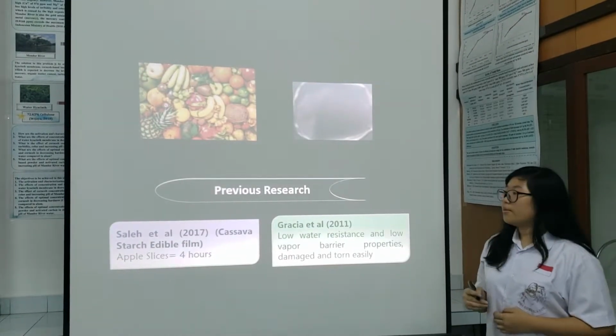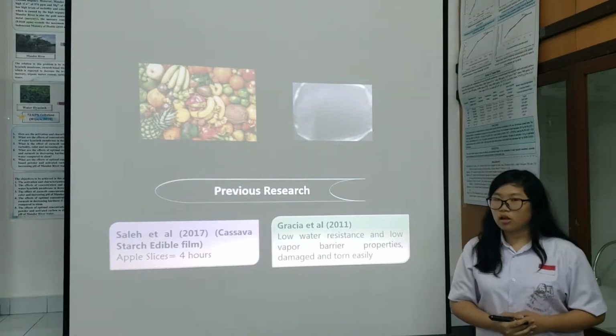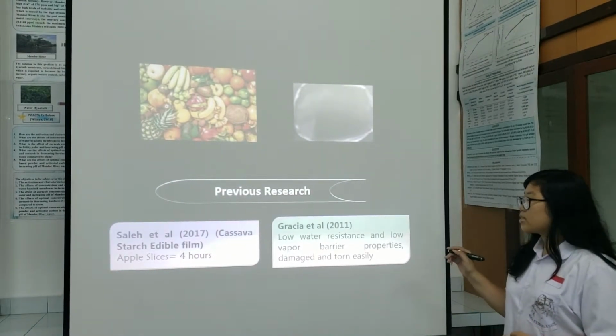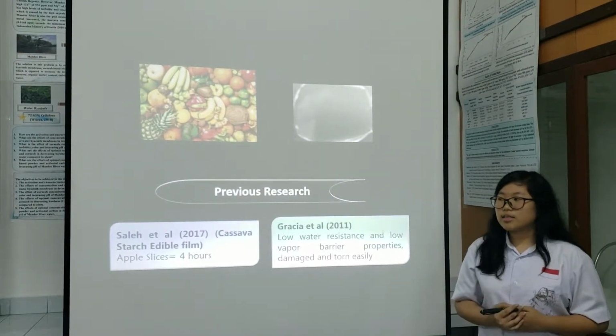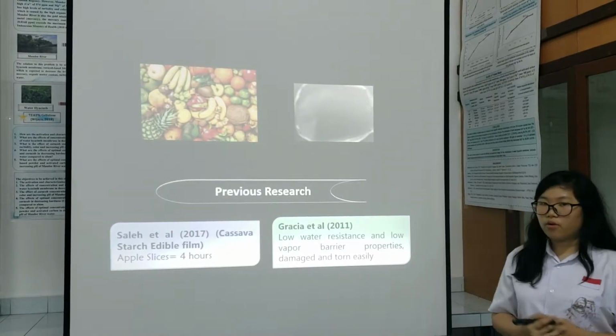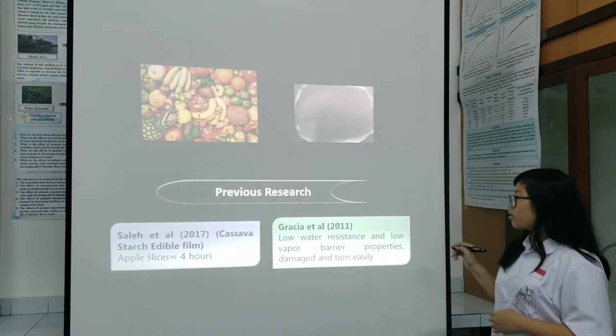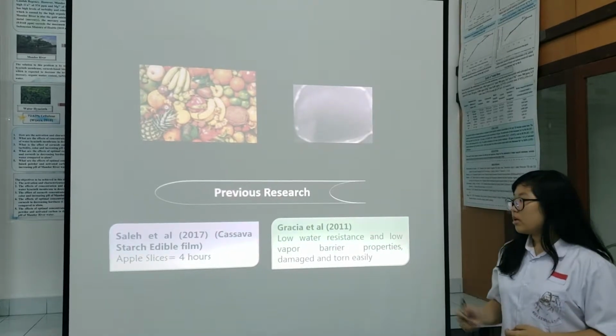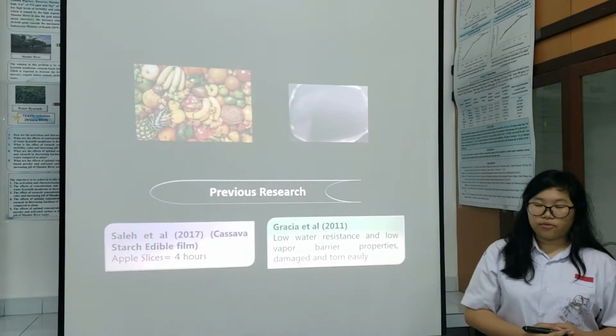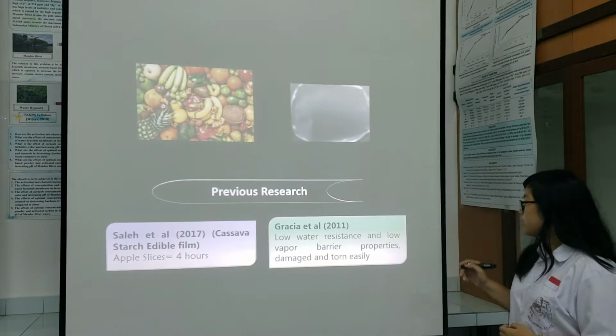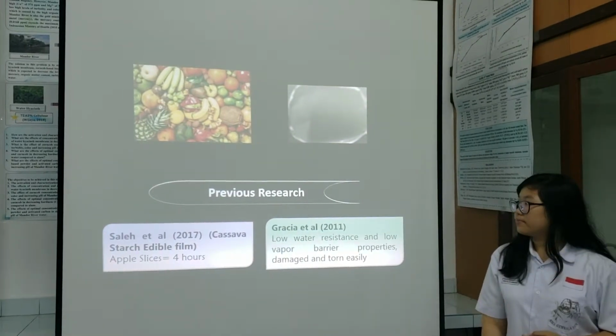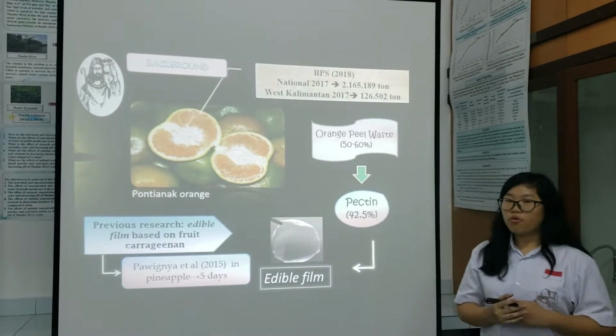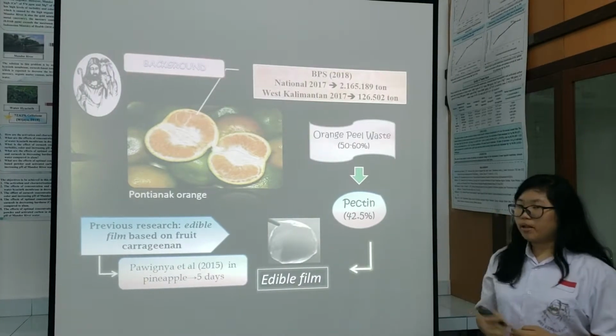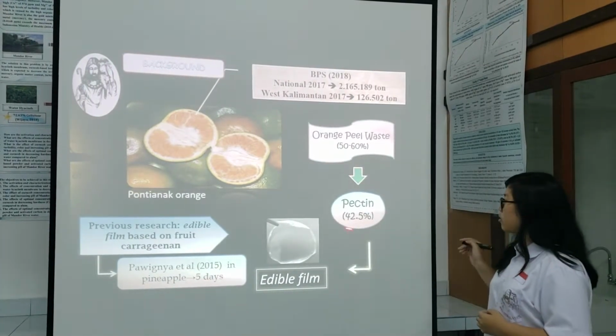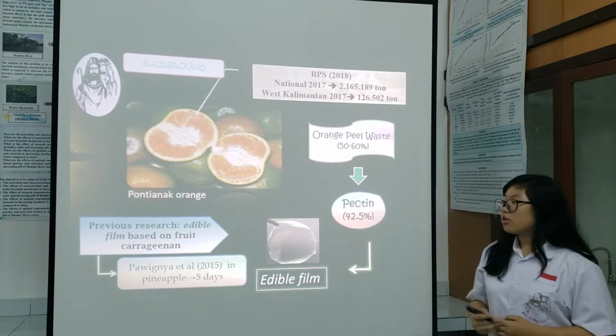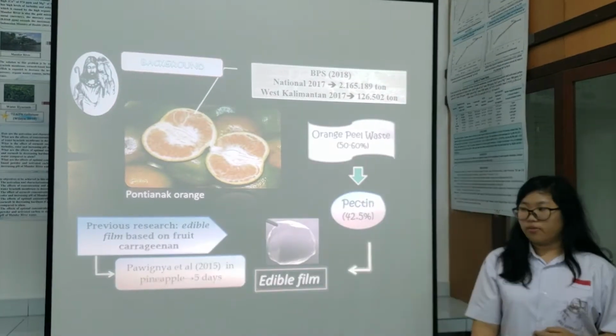Previous research about edible film had been conducted by Saleh et al. in 2017 by using cassava starch edible film, and it can extend the shelf life of apple slices for 4 hours. However, according to Gracia et al. in 2011, starch edible film still has disadvantages, such as low water resistance, so it is damaged and torn easily. Therefore, we offer a solution by using Pontianak orange peel, which contains quite high pectin, which is 42.5%, so it has the potential as the material for edible film.